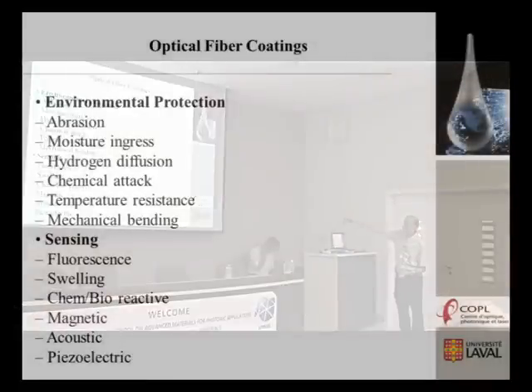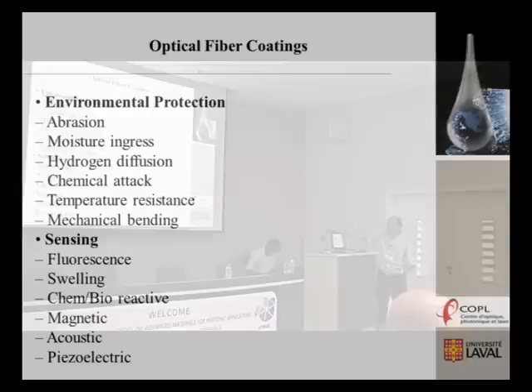Of course, one of the important things again is the coating system. The coating system depends on two points: environmental protection, and sometimes it's very important for sensing. We have different applications just using the coating, and why the protection against abrasion, against hydrogen diffusion, against chemical attacks, against temperature and mechanical bending. That's what I spoke about a little. And sensing, because sometimes we use a specific coating at the surface because we have some fluorescence, we will make some fluorescence measurement for some sensing experiments. We have some bioactive systems, and Benny spoke a little bit yesterday about that. Magnetic processes, acoustic, piezoelectric processes that we are looking for.